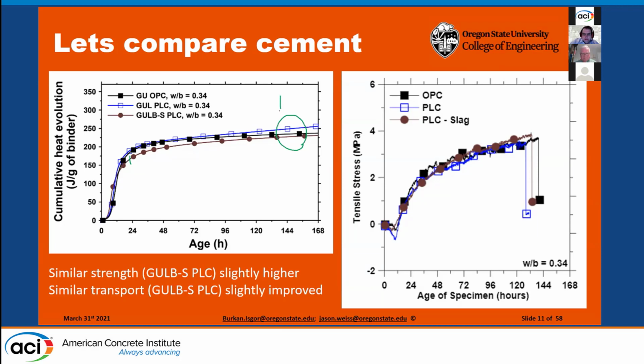But what's really interesting is this is a measure of the reactivity. The heat is a measure of reactivity. And we're getting a very similar reaction taking place in the system, but we're getting that similar reaction with a lot less clinker in the overall system. We're getting very similar strengths, as Doug showed. We're getting very similar or slightly improved transport properties when we're using the limestone with the slag in the system.